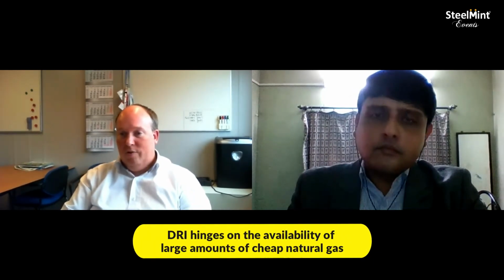Compared to DRI type processes, well, the biggest advantage of doing a process like HIsarna or any other smelting reduction or blast furnace process is that at the smelting stage, you separate the metal and the gangue or the slag component, where if you make a DRI, you do not do that separation until you do the electric arc melting stage. And then certainly if you're trying to make steel directly out of that, you need to handle that large slag volume. With respect to the DRI, if you've got cheap natural gas or cheap hydrogen available in large quantities, it is probably economically totally sensible to go that route. But it hinges on the availability of large amounts of cheap gas. And well, even though in Holland we have large gas fields, we don't have cheap gas, for example.